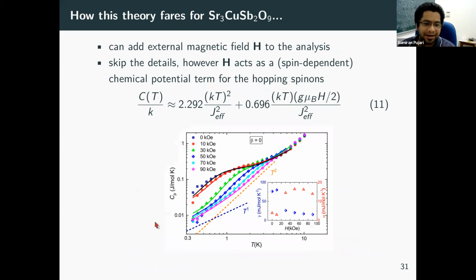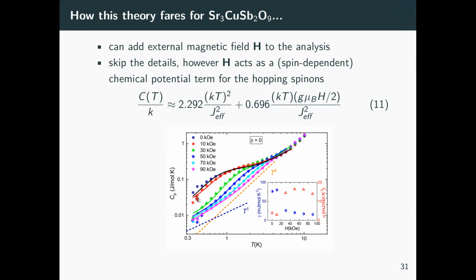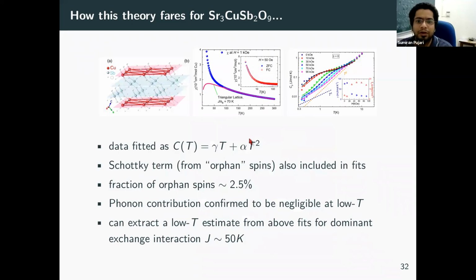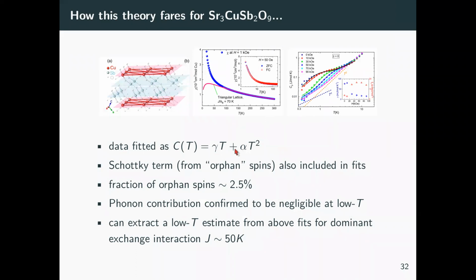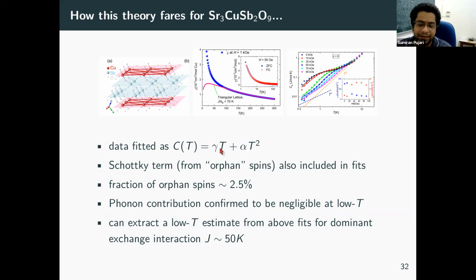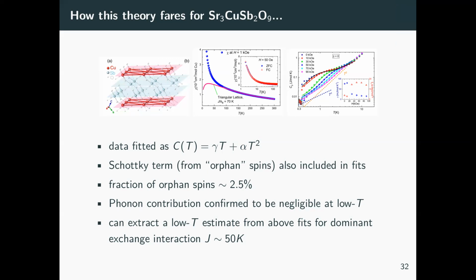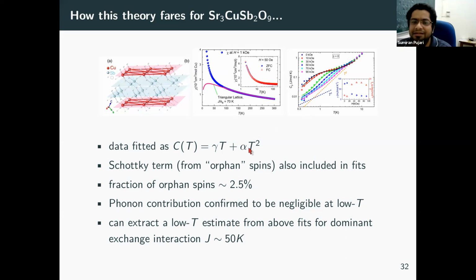Well, the way I understand it is, of course, Schottky is always present and it moves up. But you can confirm that you cannot fit the data with just pure Schottky. In fact, if they had asked us this question. If you set, for example, the linear term to 0 and you don't have these two terms, and you just try to fit the low temperature data to pure Schottky, you just miserably fail. If you try to fit the data with a Schottky component and just the linear term, it turns out you can make the 0 and 10 kilo-oersted data work. But the high temperature data again fails, and the high temperature data really needs a T-square to make it fully work. Just with pure T it also doesn't work.